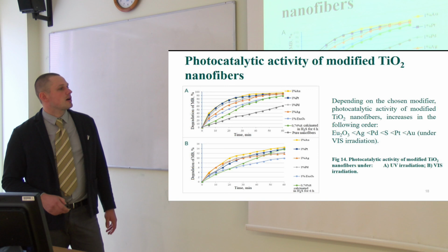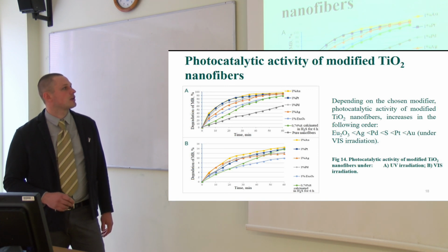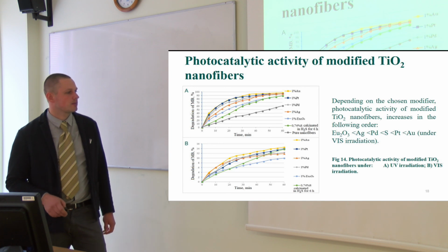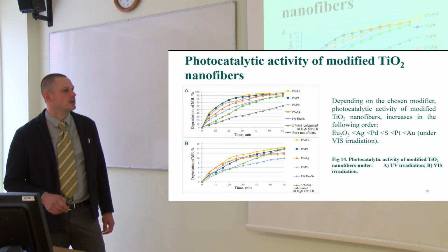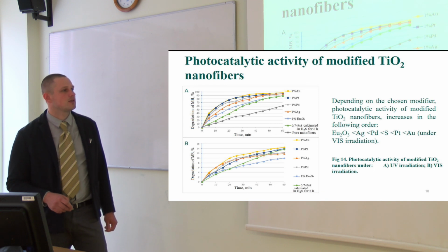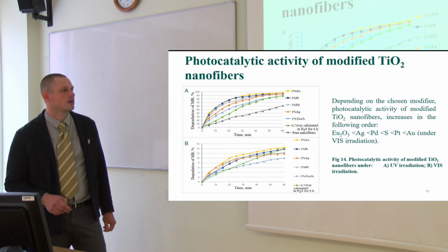So, and here you can see some part of results for titanium dioxide nanofibers modified with various modifiers under UV irradiation, under visible light irradiation. As we can see, the activity in UV light is much higher than in visible light, and materials can increase activity of titanium dioxide nanofibers in following order: europium oxide, silver, palladium, sulfur, platinum, and the most active one is gold.